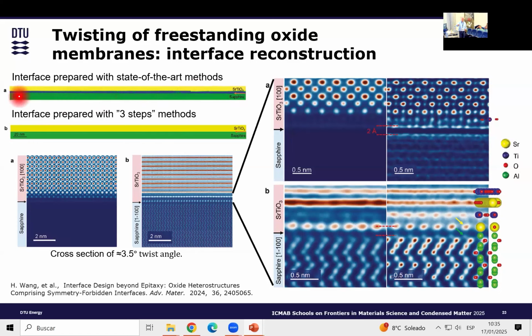So what you see here is a gap in between. The blue line is the gap, and the state-of-the-art method, as far as I understood from the paper, is just that they put the membrane on top of this, they heat it, and they see the reconstruction at the interface. Then they developed a new three-step method. The first step is annealing the substrate with laser annealing. Then the second step is putting the membrane under elevated substrate temperature. So they heated the substrate, and they put the layer at elevated temperature. And in the third step, they anneal everything with the laser, heating in oxygen. So they end up having a perfect matching.